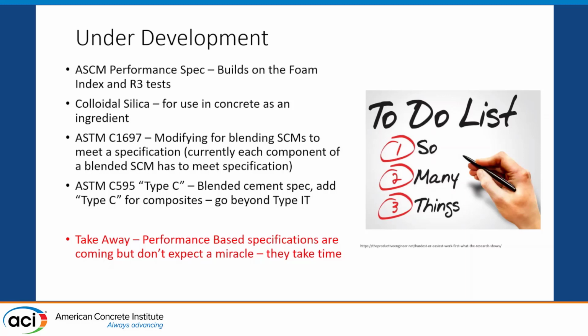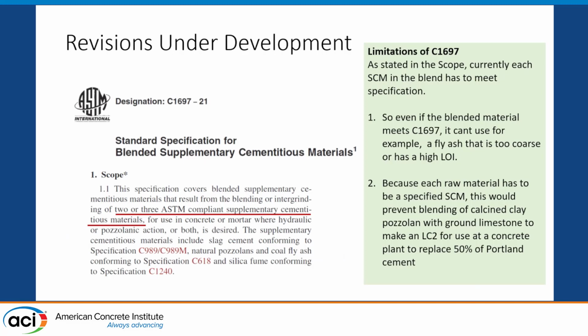We're trying to look at composite cements under C595. We're also looking at a performance spec for supplementary cementitious materials. And again, I'm trying to use this reactivity test we talked about, the foam index test, some of these things, to evaluate these new materials as a performance evaluation as opposed to saying what's in it compositionally. And that was the one I mentioned before about each one of the raw materials in that spec having to be ASTM compliant on its own, and that causes some restrictions on evaluating materials that could be used.